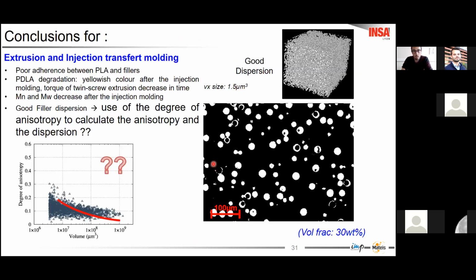So in this second study, we observe this poor adherence between the polymer and the fillers, and even with an optimized injection process, the samples had several signs of degradation. However, we obtained really good particle dispersion with this process.